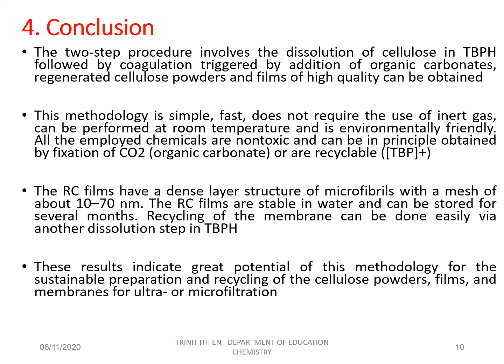A recycle of the membrane can be done easily by another dissolution step in TBPH. This result indicates the great potential of these methodologies for the sustainable preparation and recycling of cellulose powders, films, and membranes for ultra or microfiltration.